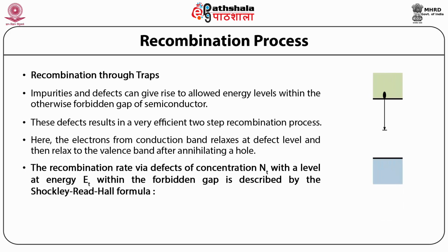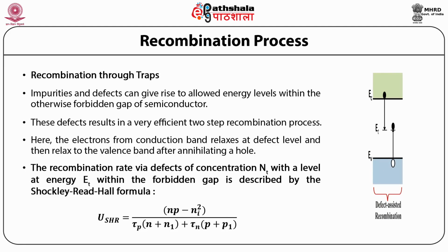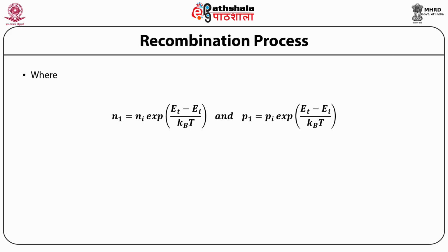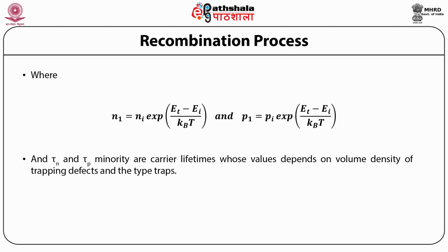the Shockley-Read-Hall formula, which is given as U SRH is equal to (Np minus Ni square), the whole divided by tau p multiplied by (n plus n1) plus tau n multiplied by (p plus p1), where n1 is equal to Ni exponential (Et minus Ei) by kT and p1 is equal to Pi exponential (Et minus Ei) by kT. And tau n and tau p are the minority carrier lifetimes whose values depend on the volume density of the trapping defects and the type of traps.